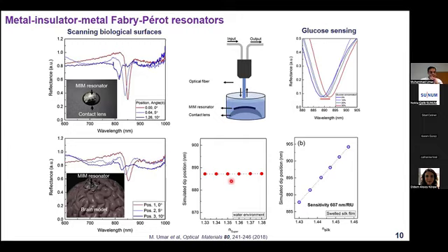And then we also checked that if we only change the refractive index of the background, there is no effect on the insulator. We checked by simulation that there is no effect on the wavelength of the resonator. So this means the silk, or polymer, is the basic element in this case. The water is changing the refractive index of the polymer, and it is also increasing the thickness of the polymer. That is the major principle of this device.